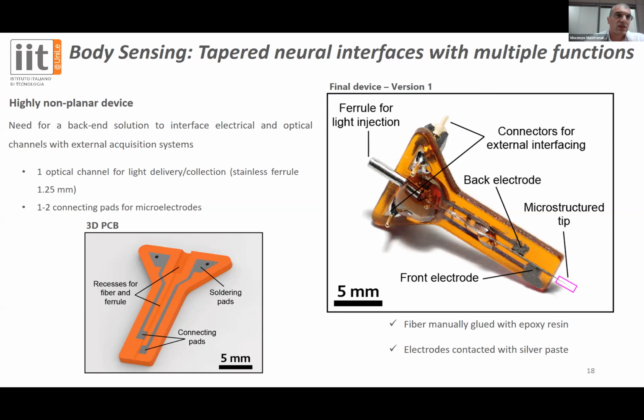The limitations of this first generation of this packaging are mainly due to the gluing system of the fiber, the optical fiber inside the PCB. And in this case, the fiber was manually glued with epoxy resin, and also the connection between the connecting pads and microstructured electrodes was made by using silver paste. So it is a process that is not very clean and robust.